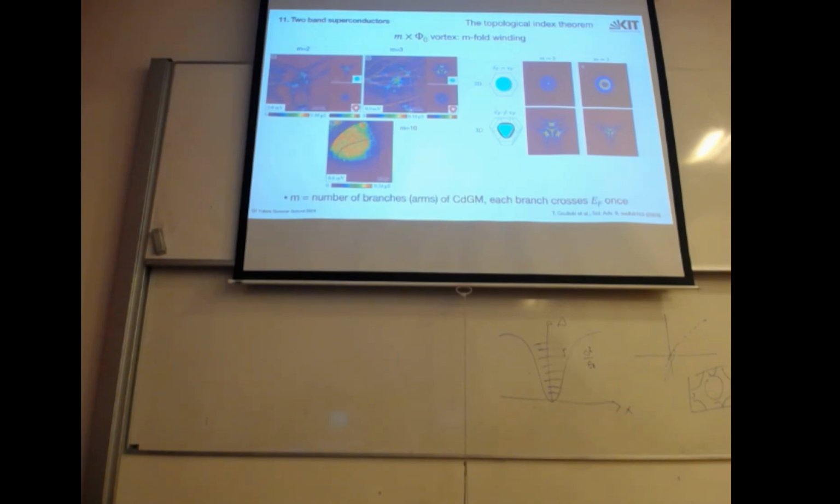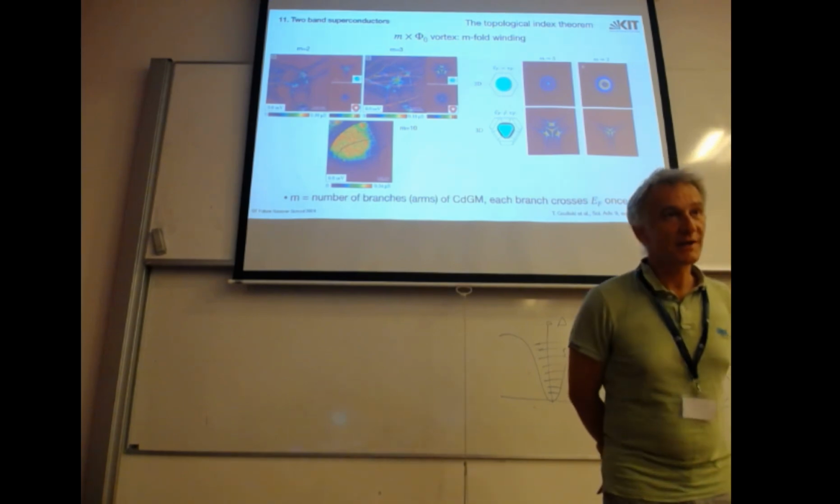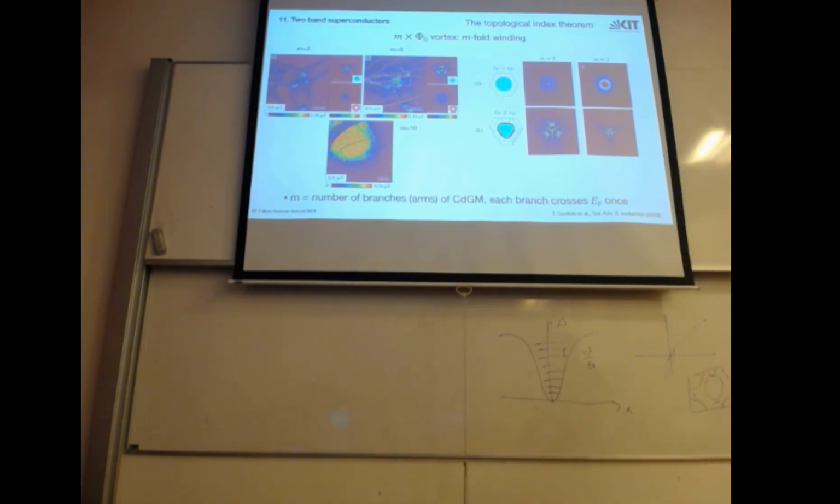So coherence lengths are pretty small, so there's a lot of scattering going on even in clean niobium, as clean as we can get it. So this seems to wash out this multi-band stuff. Lead is so clean and the coherence length is so large that we can clearly see these two bands. Niobium is also a two-band superconductor, but interband coupling is so strong that you have just one condensate. They are not separate.